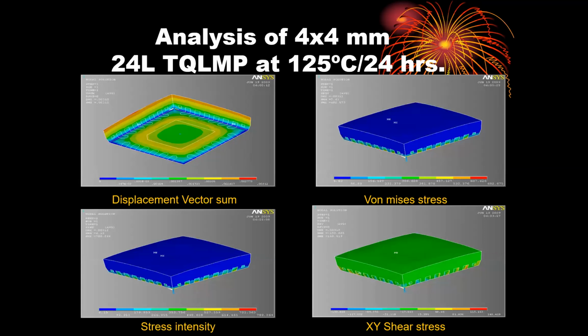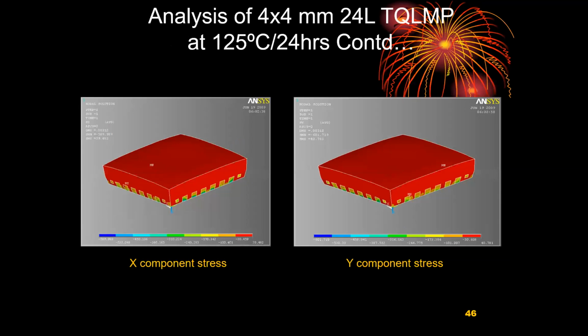Coming to the analysis of the 4 by 4 mm TQLMP at about 125 degrees Celsius for 24 hours, which is not necessary actually, but we just punished it unnecessarily to see what would happen to the reliability of the IC when you apply failure analysis. The analysis of the 24L TQLMP has also given us a lot of interesting results.